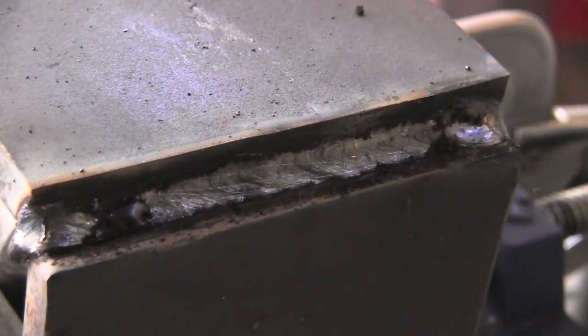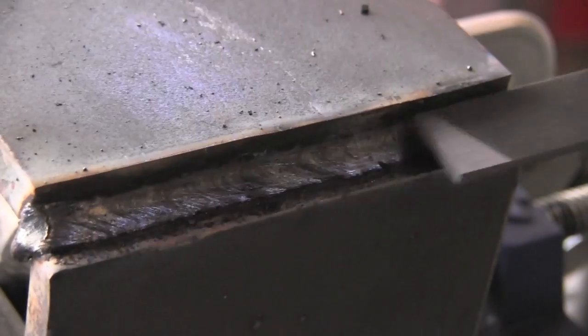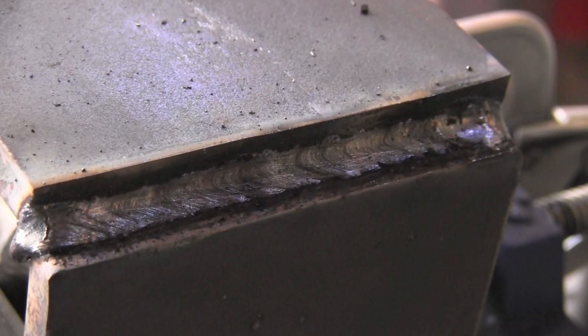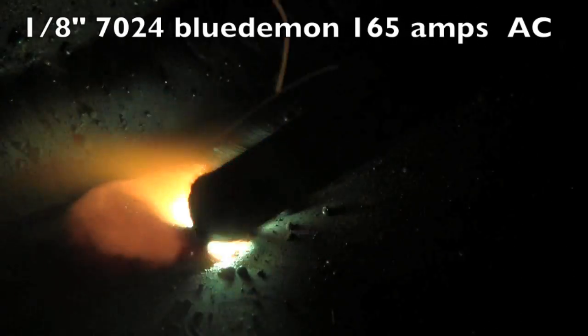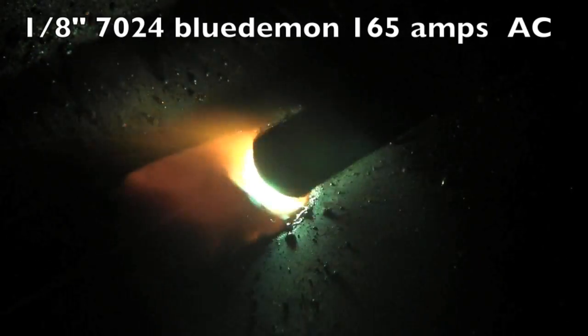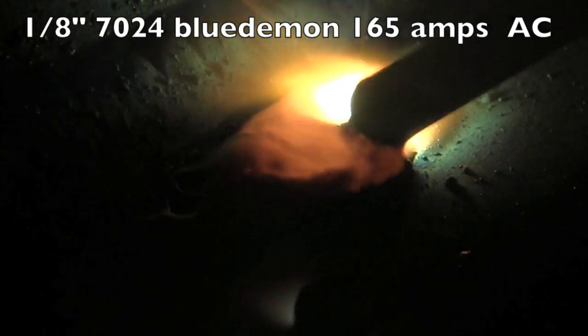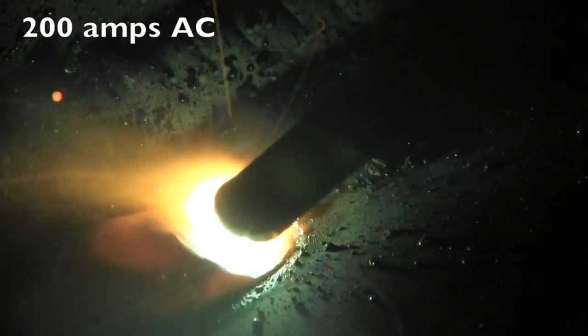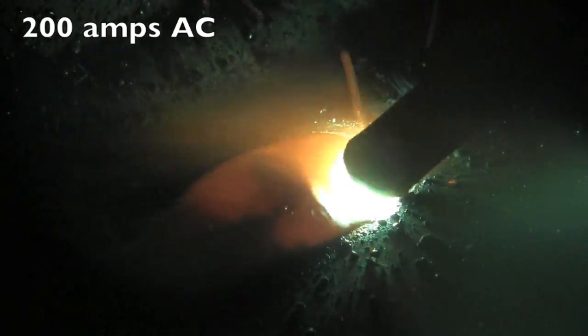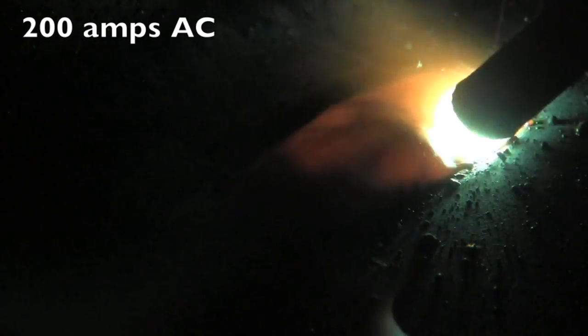I had to crank it up a lot hotter than I thought I should to get that slag pushed away. 200 amps on AC is what I'm using on this 1/8 rod, and that's just more than it should take. And it's just not welding all that great. Slag should be coming off there a lot easier than that. Granted, it's kind of hot, but this is at 165 amps, and watch right here, all that flux and slag just swirling around there. I had to crank it up to 200 to get enough arc force to keep it all pushed back to the back of the puddle.